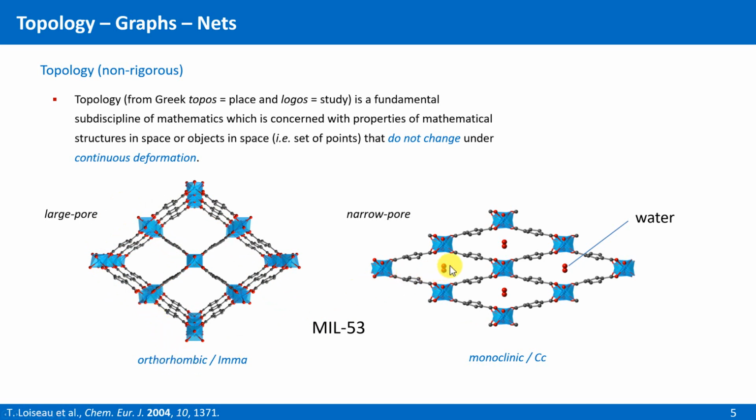But now, if we adsorb small molecules like water or CO2, then this MIL-53 undergoes a dramatic phase transition to this narrow pore state. So the MOF breathes out. Although somehow opposed to human breathing, because this happens while molecules are inhaled, so to speak. But anyway, the unit cell considerably shrinks, and the extent of the volume change of the unit cell is, or at least was, unprecedented.